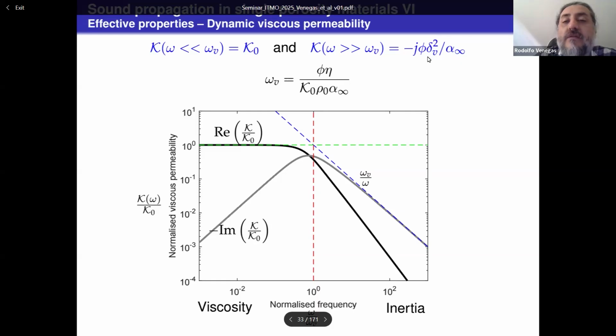And at high frequencies, it tends to a purely imaginary value shown by this, where delta V is the viscous boundary layer and alpha infinite is the tortuosity. So the transition between these two regimes is given by this Biot characteristic frequency, where phi is the porosity, eta is the dynamic viscosity, and rho naught is the equilibrium density. For frequencies much smaller than this Biot frequency, the permeability tends to its static value, and we will say that this is determined by the viscosity of the fluid.